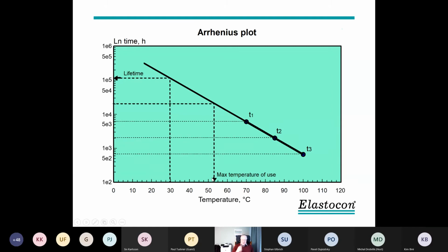And if we use that, we find that this material is not really good, much over 50 Celsius. But if we look then at the car industry, they often only use 1,000 hours. And that is down here. If we use 1,000 hours, then the maximum temperature use is 95 something. So if you see a figure telling you what the max temperature use is, always ask how long, for how long time. It's often not 2.5 years.